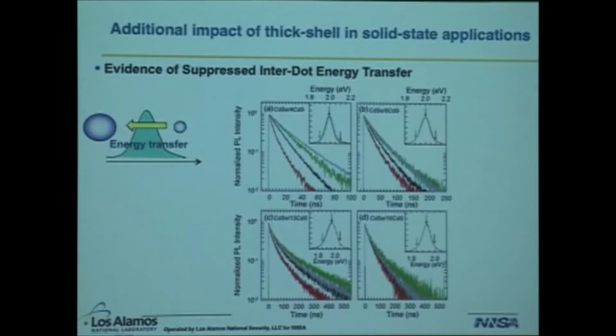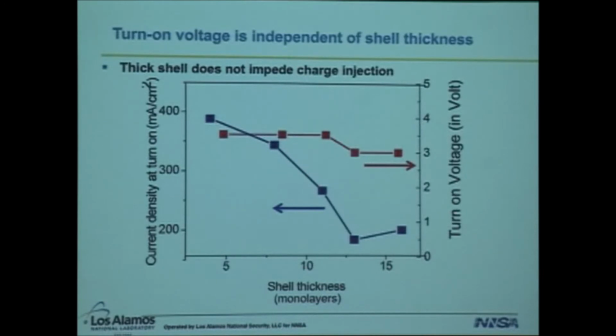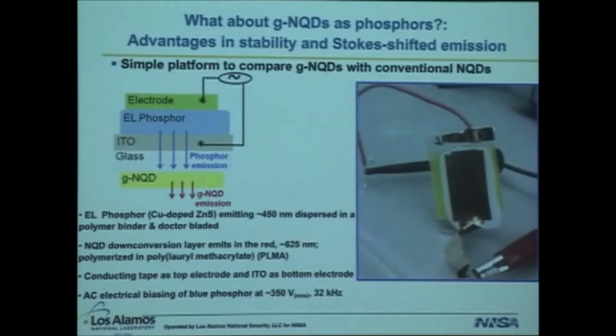This is some of our energy transfer studies where we definitely showed that energy transfer is effectively turned off in the thick shell systems. So do we have an issue in terms of the thick shell impeding charge injection? The answer seems to be no. Our turn-on voltage is about the same all the way across the series, so that's good news there. And then I think I'll fly through this.